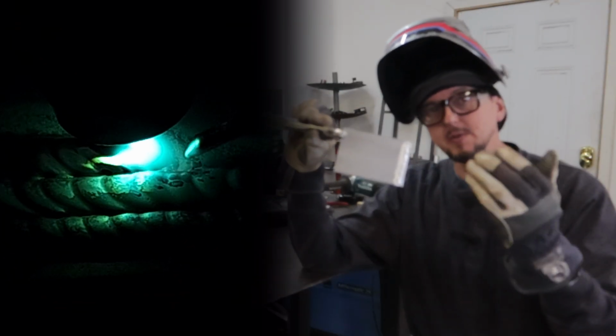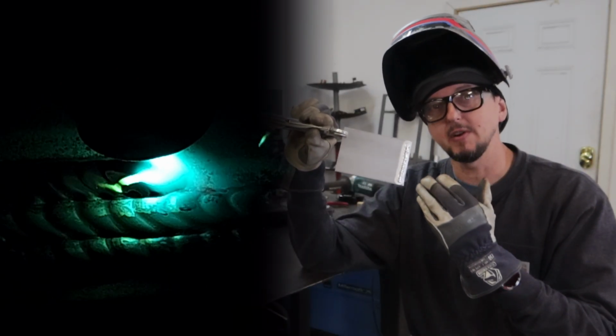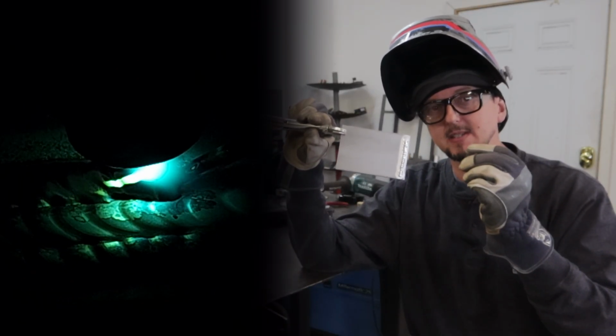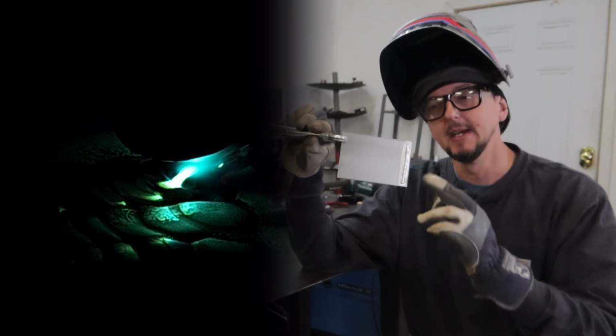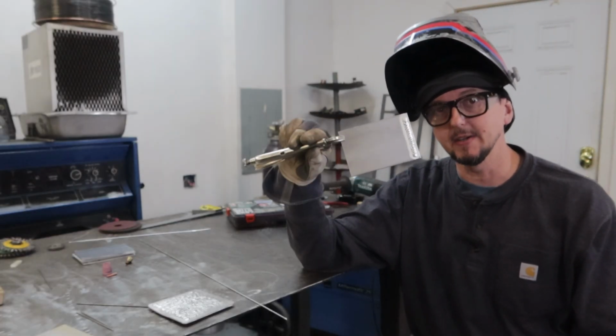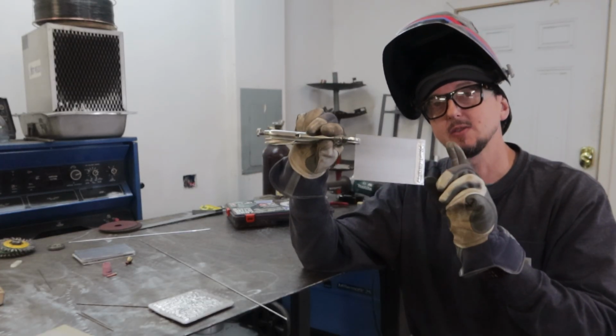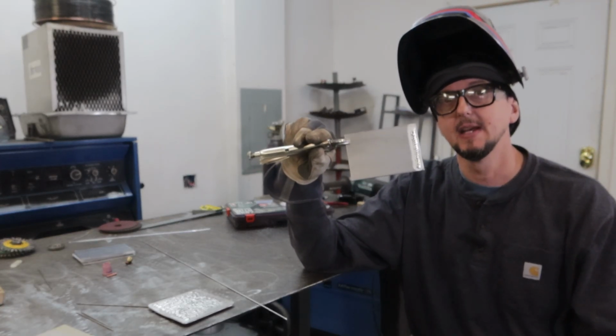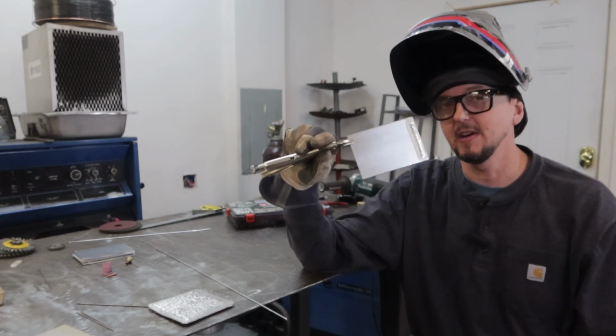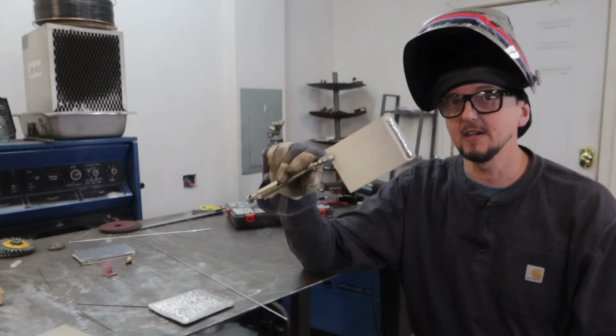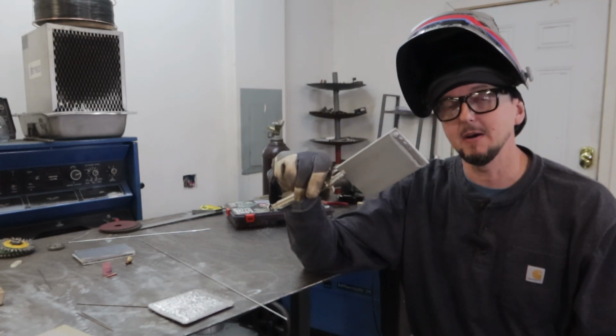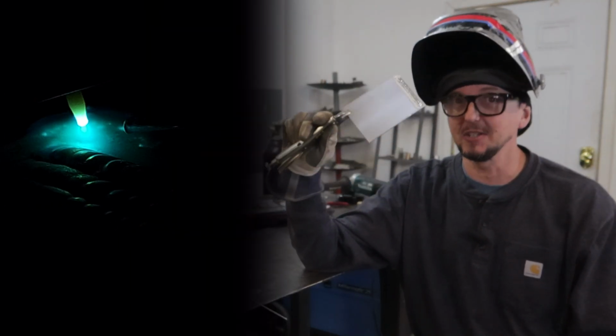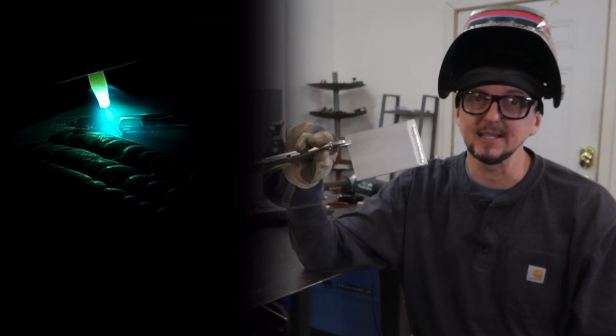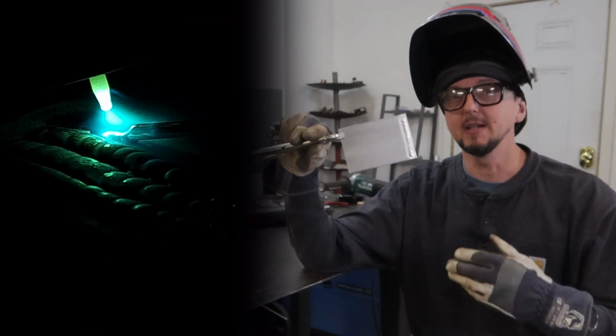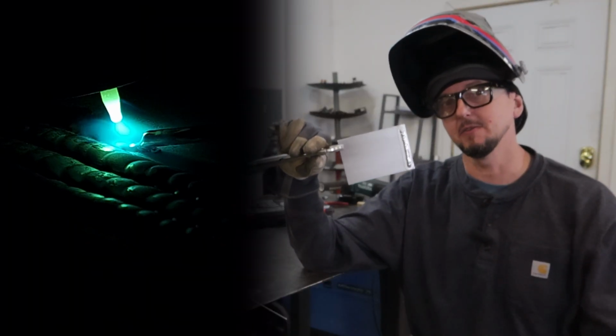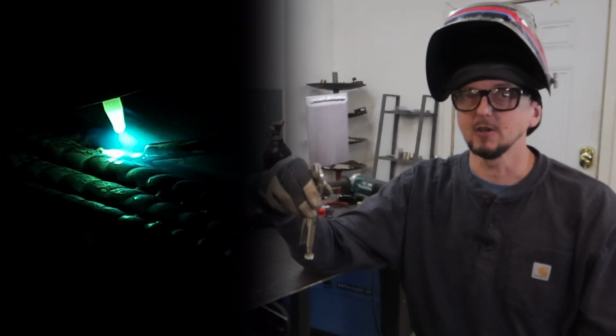And then I also, if we're using a pedal, I like to back off of that amperage very slowly and even move my tungsten around just slightly to agitate that weld pool a little bit to reduce the amount of cratering. The problem with the crater is that that's where cracks will propagate in our aluminum welds, especially if the amount of filler is very thin there. So make sure that you're filling your craters and that you're developing that good habit right now, because the habits that you develop now, especially when you're first starting out on something like this, where you're doing a lot of repetition, you want to develop those good habits so that you have that muscle memory of filling your craters.